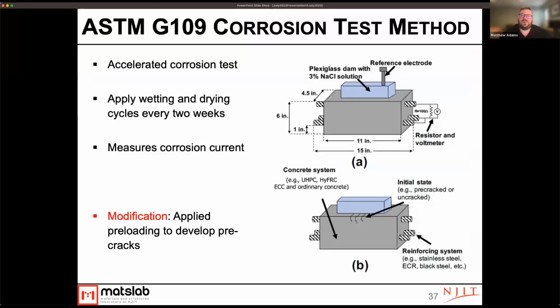So one of the first things we started running were these G109 corrosion tests, and Matt talked about this a little bit, but this is essentially an accelerated corrosion test where you apply a dam at the top of a reinforced prism. In that dam, you have a chloride solution that you put on for 2 weeks at a time, allowing it to stay wet and then drying it. And this helps to accelerate the rate at which those chlorides move into the system. And then we measure the corrosion current density along the rebar, and that will tell us when corrosion has likely occurred. So the normal test method does not have you apply any preloading to develop cracks.